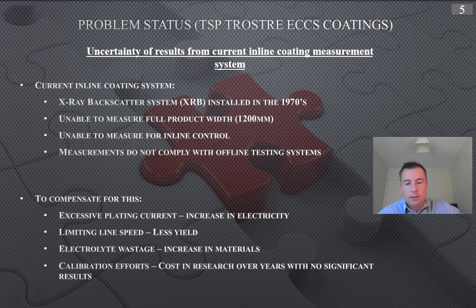So the problem that TATA Steel Packaging in South Wales is facing is in relation to these chromium coatings. On their production line, they've got an X-ray backscatter system, which was installed in the 1970s. What this does is measure the center line of the product only to measure this chromium coating. Like I said previously, these chromium coatings are a maximum of 20 nanometers thickness, so very small. The issue they're having is that when they're doing periodic offline testing every 12 hours with other coating thickness measurement methods, the inline results are not compliant with the offline results. So it's a big problem.